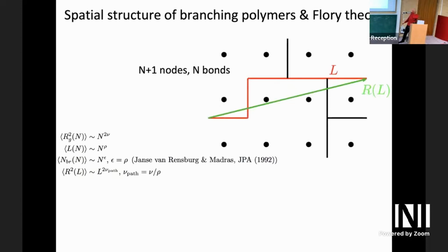First of all, one needs to understand the physics of randomly branching polymers. I started this because the rings somehow behave like randomly branching polymers. So forget about the rings; let's consider only the branched structure. Branching polymers are interesting because they are classical systems in polymer physics, and because their physics is much richer than that of ordinary linear polymers. In a linear polymer you have only one exponent, the exponent nu, that describes how the typical polymer size grows.